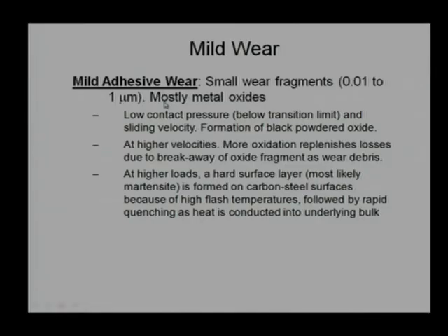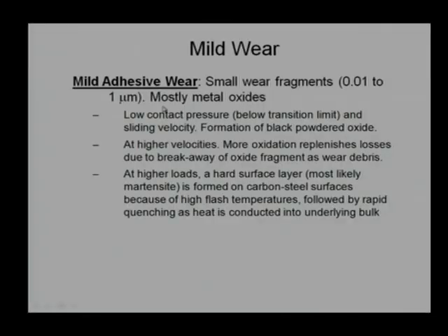Again, another point is that mostly these particles are metal oxides, not pure metal; the material gets oxidized and comes out. In other words, to reduce the friction, we allow exposure of the material to the environment so that it can form some oxide, reduce the shear strength of the interface, and reduce the friction coefficient. In that case, that also leads to the initial wear, where the wear